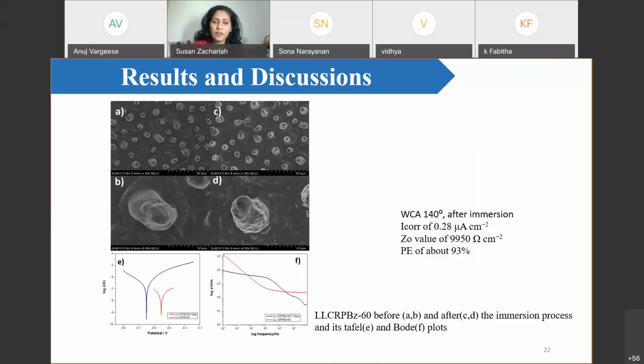And here we have soaked the PVC coated CRS in NaOH for 7 days, and we checked whether it shows good characteristics as before. We found the water contact angle reduced to 140, but it was still okay even after 7 days, and we obtained a protection efficiency of 93%. So this reduction must be because of some problem that happened on the surface.